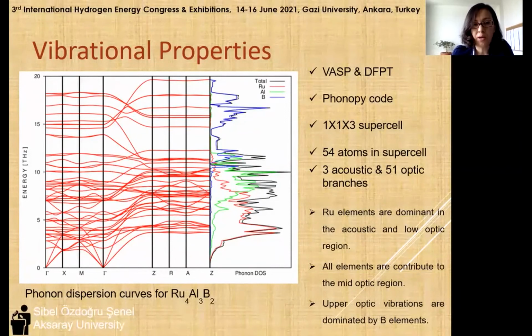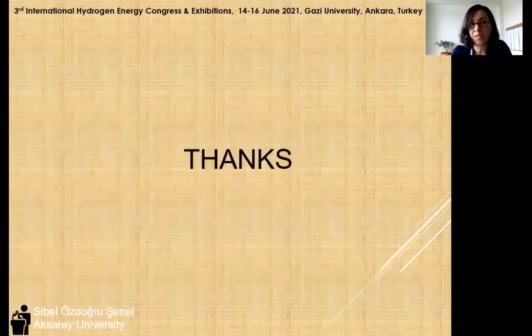There are 54 atoms in the supercell, with 3 acoustic and 51 optic branches. It seems that ruthenium elements are dominant in the acoustic and low optic region. All elements contribute to the mid-optic region, and upper optic vibrations are dominated by boron elements. Thanks for listening.